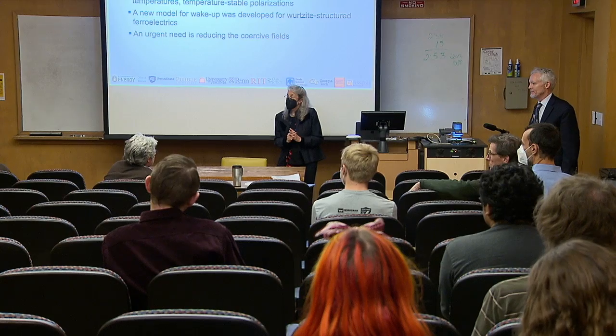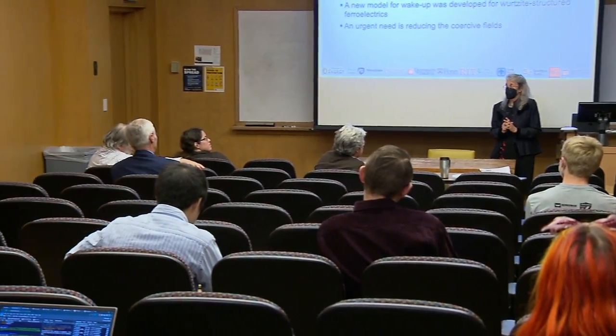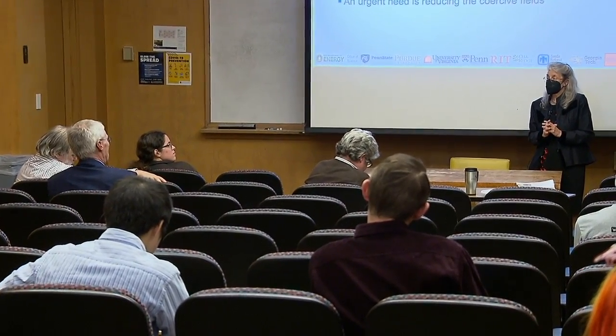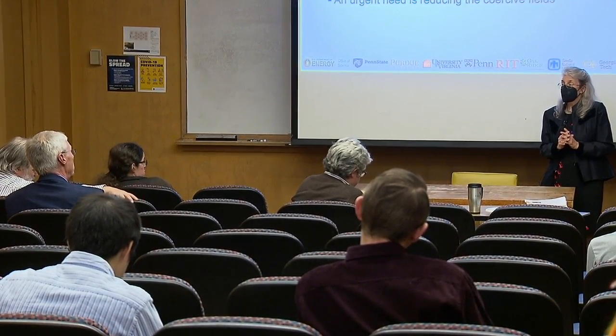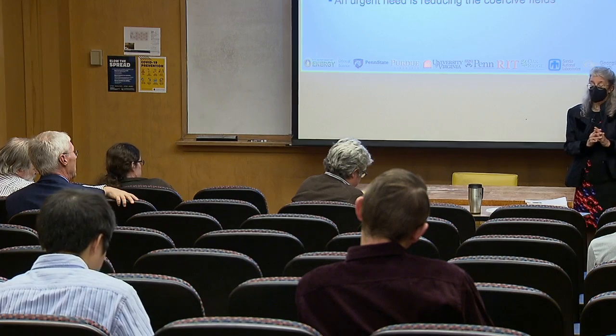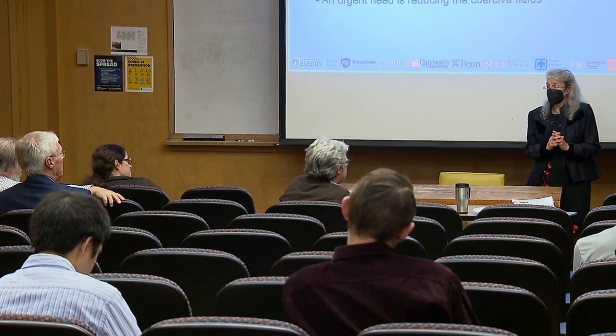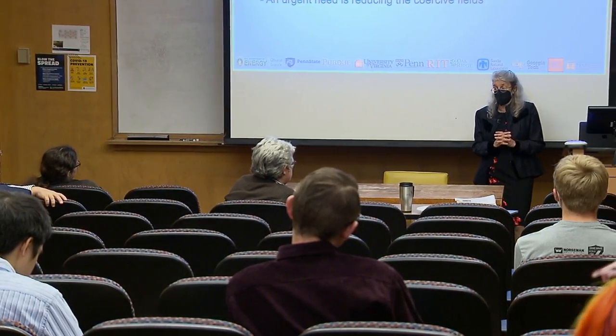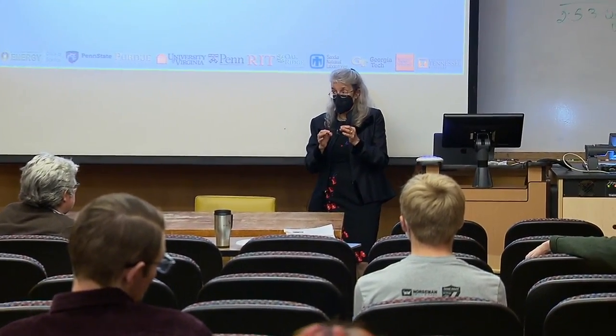Susan, you said it's very hard to verify the switching mechanism related to boron, for instance. I'm wondering whether that wouldn't be a nice system for a direct atomic resolution imaging experiment in one of these super in situ transmission electron microscopes. So we're trying that experiment. Elizabeth Dickey from Carnegie Mellon is the one who's doing the work. The challenge is that these materials are granular, which means that the columns are tens of nanometers in thickness. It's actually hard to thin it to a single column in thickness. And when you end up overlaying two columns, it's really hard to find the wall motion. So we're trying, we're not there yet.